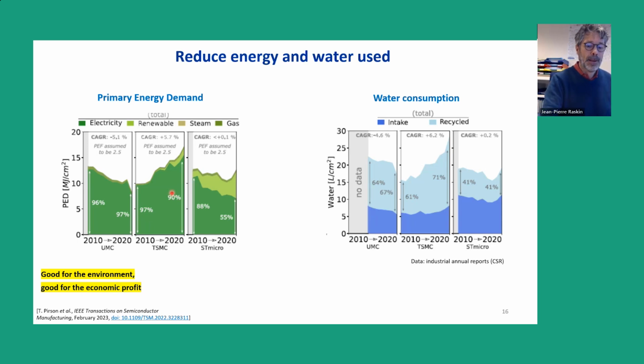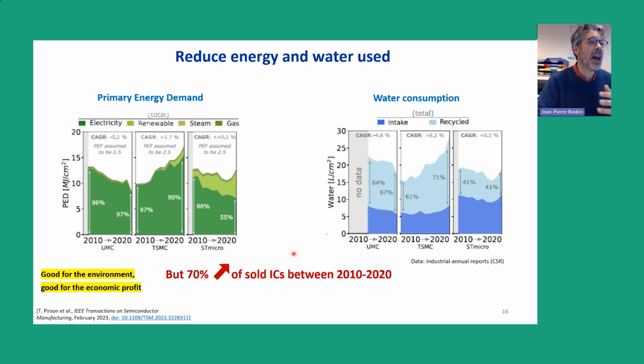integrated circuits. But what we have to keep in mind when you read those kinds of reports, you can see here that the units used for the energy consumed and for the water consumption are megajoule per centimeter square of wafer, and the same thing here, it's per unit area. But knowing that during the same period of time, we have an increase by 70% of the sales of integrated circuits, unfortunately, even if they make a lot of efforts to reduce the resources used in the processing of those ICs, because the sales of ICs has been increasing drastically during the same period of time, we have an absolute increase of electricity and water consumption.